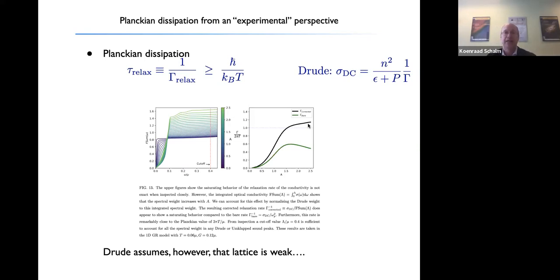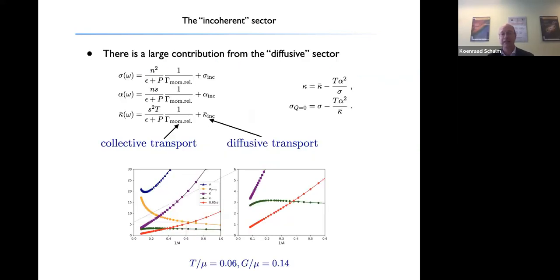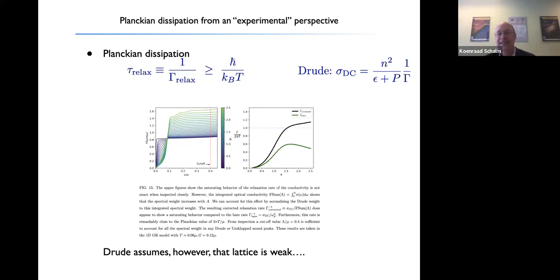This is supposed to be the maximal dissipation rate in the system. This is the Planckian dissipation rate, where the dissipation is completely set in terms of natural constants, and there's no intrinsic energy scale left. So if you would not have analyzed the optical conductivity in this system, or not done this more careful disentangling of the diffusive and the collective transport, you would say that this is a classic example of Planckian dissipation in the system. But you have to be more careful, because this is based on an extraction of this relaxation rate through the Drude mechanism. And Drude, of course, assumes that the lattice is weak, and that is not the case here.